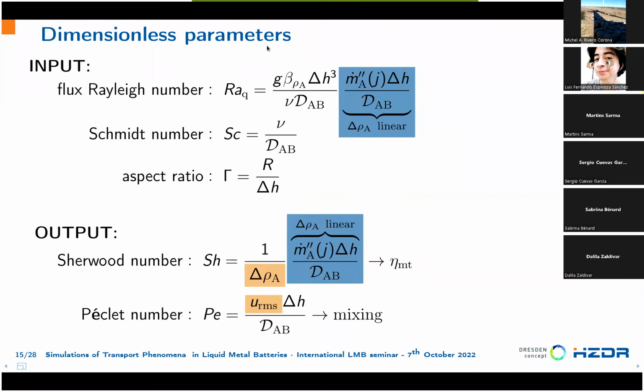And so what are the parameters that describe the phenomena? The first parameter is a Rayleigh number that differs a bit from the classical Rayleigh number that we see in classical Rayleigh-Benard convection. So we don't have here a temperature difference or a concentration difference, but we have a function of the mass flux at the interface. So this is a concentration difference computed under the assumption that the mass flux across the layer is linear. This overestimates a lot the concentration difference, it is even larger than the one that we observed during diffusion, but it's important to parameterize the problem. So the Rayleigh number in some way will be our forcing parameter, and it will contain the current density inside. It will be a linear function of the current density.